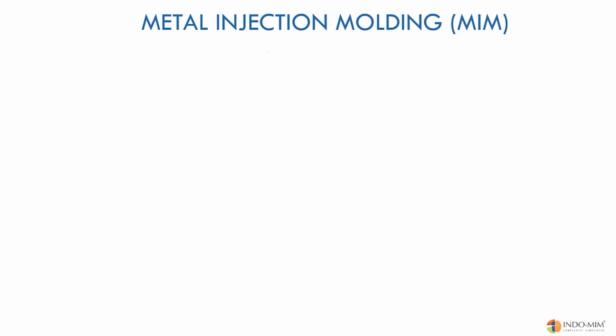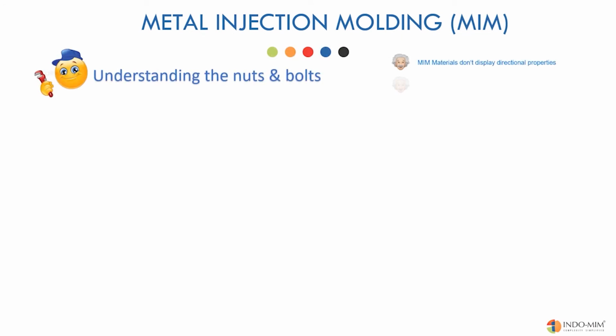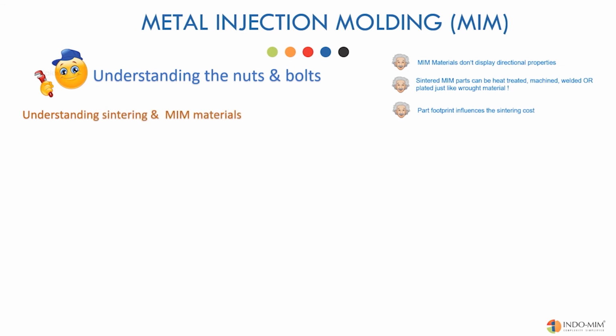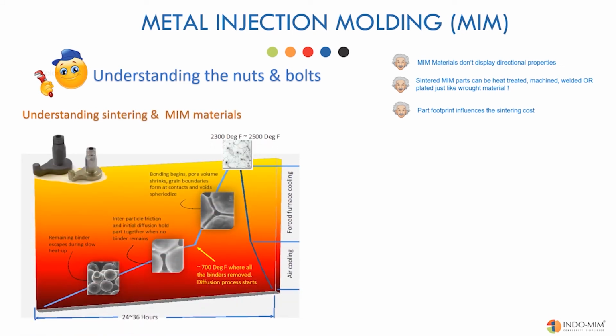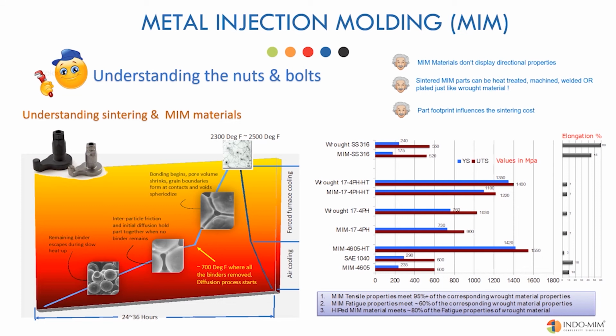Post-sintering, MIM materials achieve minimum 97% density. After sintering, the components are 100% metal, all binders gone. The remnant porosity in the material is not interconnected, hence, it doesn't influence the material properties in any significant way. As you can see, MIM materials achieve 95% of the corresponding wrought material properties. For most applications, this is acceptable.